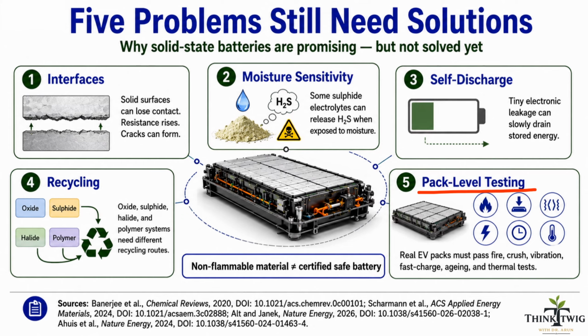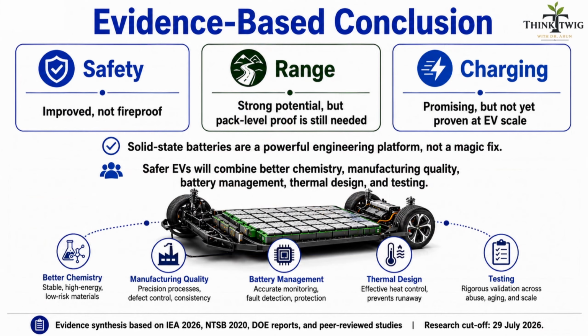Fifth is full pack testing. The battery must survive fire, crush, vibration, fast charging, aging, heat, humidity, and real road conditions. A non flammable material is a good start, but it is not a safety certificate. So, will solid state batteries solve EV fires? Not completely. They can remove one major flammable component, the liquid electrolyte, and they may also reduce heat release in some failure conditions. But the risk does not disappear. Internal short circuits can still happen, lithium metal can still react strongly, and the cathode can still overheat.